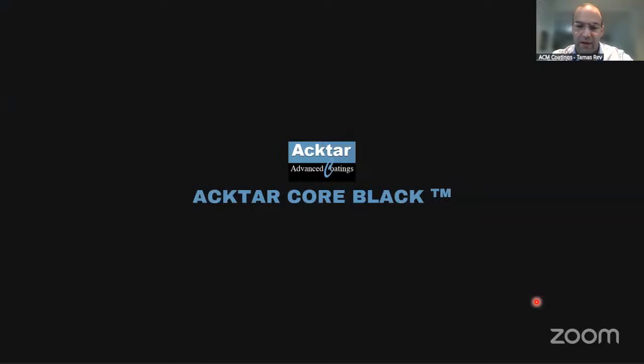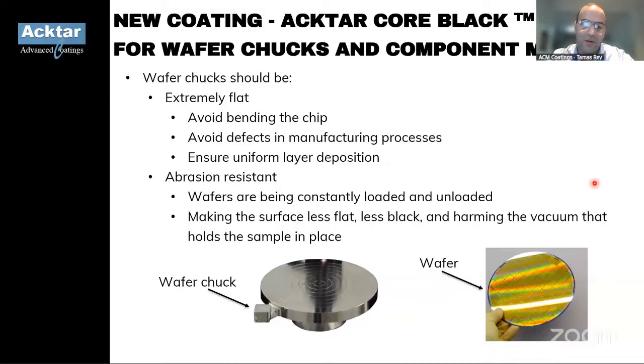So with that, I want to introduce one of our new coating types for these directly applied coatings, which is called Acktar Core Black. Acktar Core Black is a new coating especially designed for wafer chucks and component mounting. You can see a wafer chuck here and the silicon wafer here. As we know, wafer chucks should be extremely flat, especially to avoid bending the chip, to avoid defects in the manufacturing processes, and to ensure uniform layer deposition. They also have to be abrasion resistant, especially because wafers are constantly loaded and unloaded. Wear makes the surface less flat, less black, and it harms the vacuum that holds the sample in place.